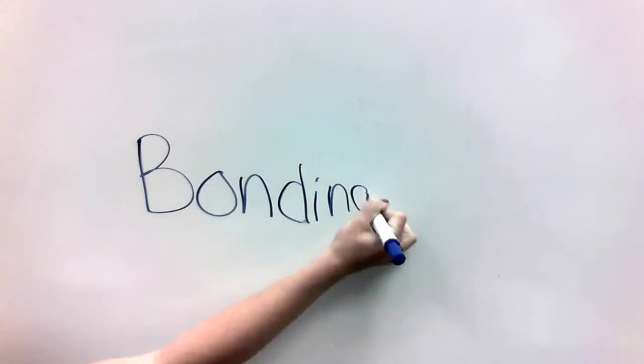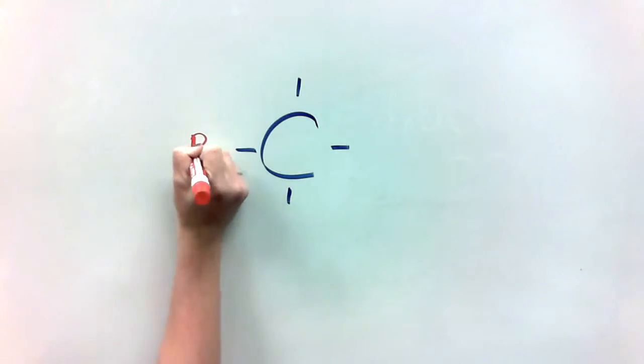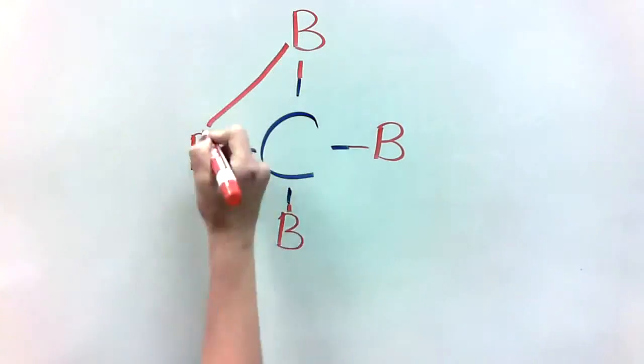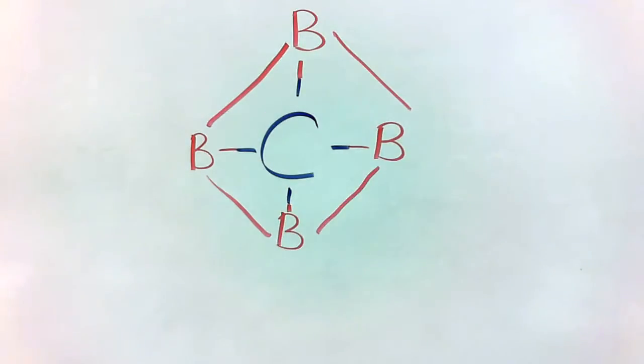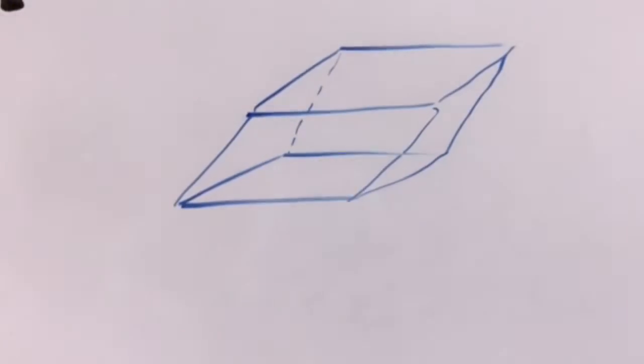Boron carbide is formed through a strongly exothermic chemical reaction. It ideally forms a rhombohedral unit cell of 15 atoms in a ratio of 12 borons to 3 carbons. The atoms bond in one icosahedral boron unit and then a linear carbon-boron-carbon chain.